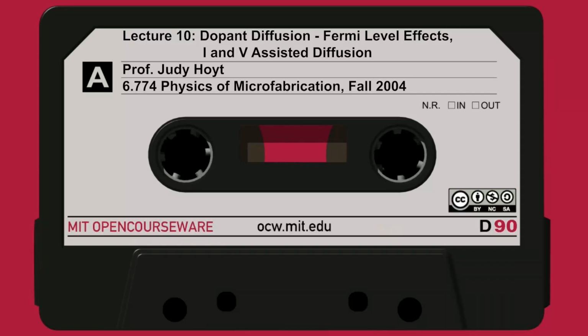Here's the boron profile. It's kind of Gaussian-ish, sort of, but it has this little dip in it right here, this divot. Right where the PN junction, the metallurgical junction, happens. And in fact, this little divot is due to the electric field effects, which significantly impact the boron profile near the junction. Remember, the electric field here is being generated mostly by this rapidly decreasing arsenic concentration, and the boron feels that and its diffusion gets modified.